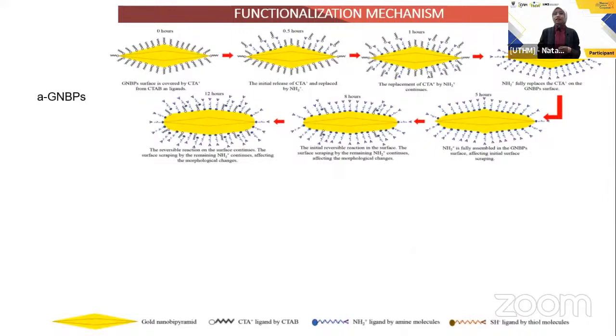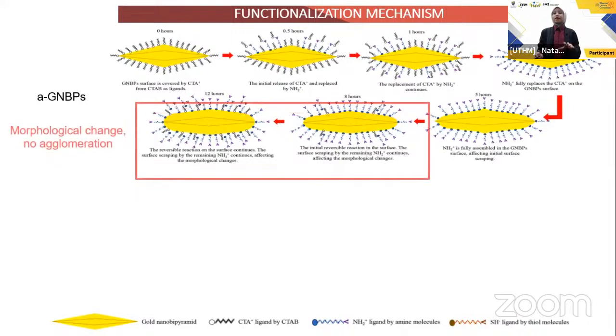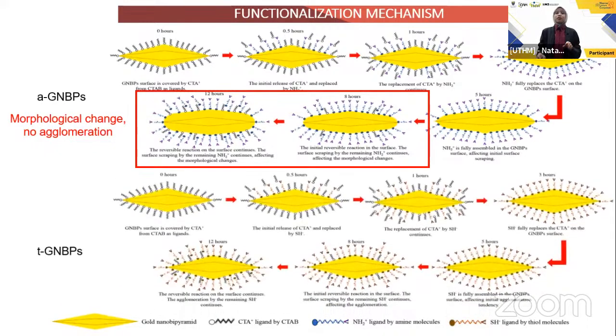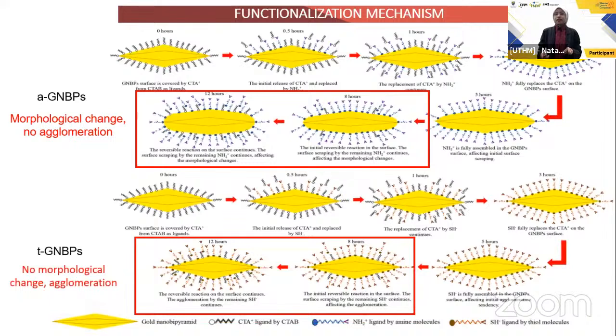Okay, we already know how to synthesize and functionalize the surface of gold nanobipyramids, and we also know about the properties change after the functionalization process. And here is the mechanism for the functionalization process itself. Based on the characterization results, amine groups influence the morphological change, while thiol influences the nanoparticle agglomeration. This phenomenon also corresponds with the general understanding of zeta potential value, where the positive charge of amine inhibits nanoparticle agglomeration and vice versa for the negative charge of thiol.